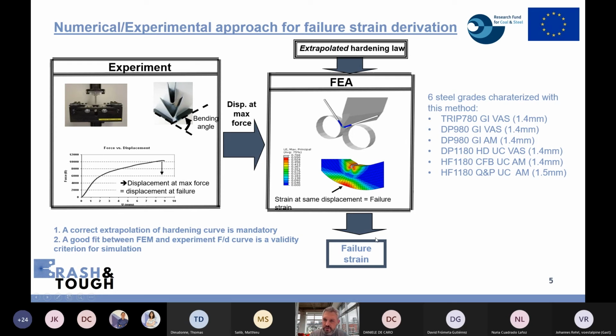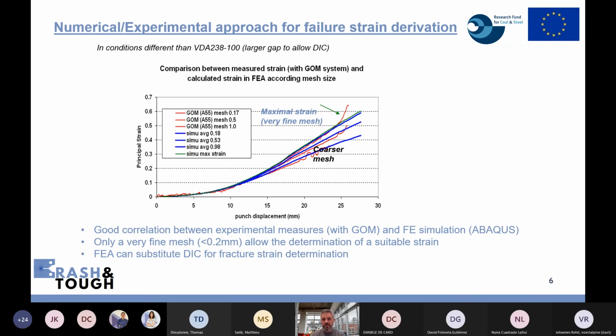So this approach was applied on the 6 steel grades: the TRIP 800 from voestalpine, DP 1000 from both steel makers, and 1100 grades also from both steel makers. And we will have some comparison of these results. But first, it's also interesting to have some validation of this approach. So this was done a couple of years ago at ArcelorMittal.